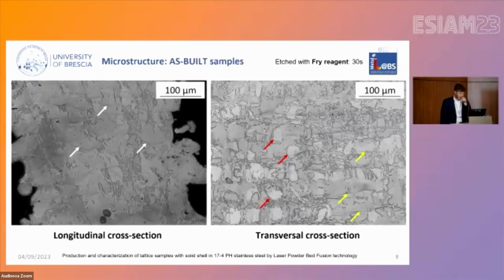So let's start with the analysis of the microstructure. At the beginning, we can see the longitudinal and cross-sections of the samples, etched with Fry's reagent for 30 seconds, and we can detect in the longitudinal cross-section, in particular with the white arrows, the typical overlapped melt pools of the process, due to the laser energy that melted the powder locally. After that, in the transversal cross-section, we can see the scan tracks of the laser, which show the path of the laser during the process, indicated with the yellow arrows, while with the red arrows, we can see the columnar grains.